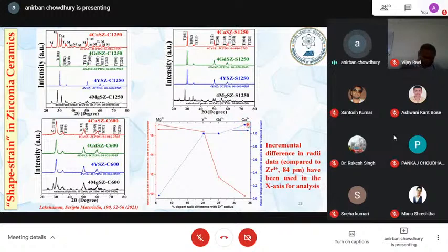And how is calcia capable of doing this? Because we found out and we have shown that calcia has the highest control in grain boundary mobility of the zirconia grains. That's how you control the zirconia grains in here using calcia. When you can do that, then you have this success. So we understood that calcia got stabilized because of this method. So then this 4% or 3%.